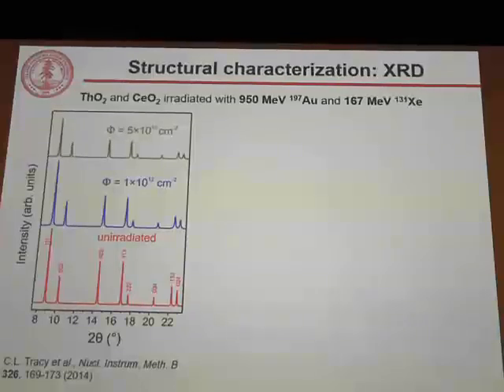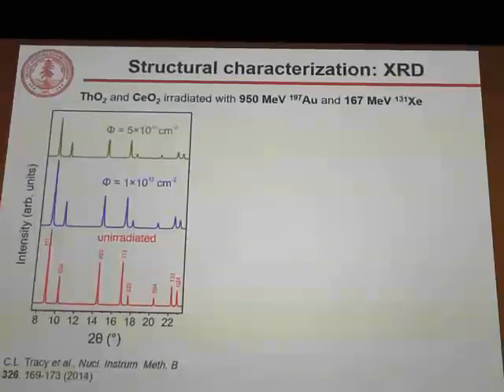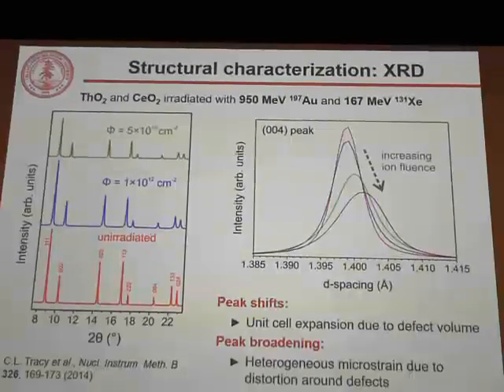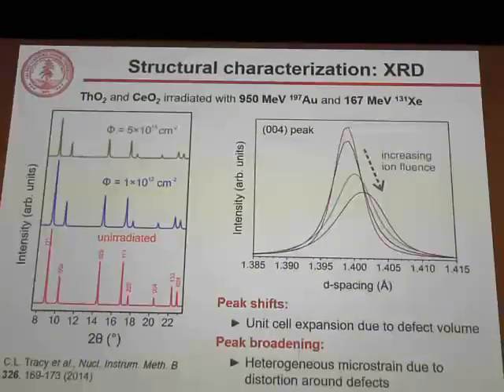And you see there's actually very little change in the pattern. The fluorite structure is retained under irradiation, which is nice for nuclear fuels. Of course, you want them to retain their structures. But if we look very closely, we do see two small changes to the X-ray diffraction maxima.